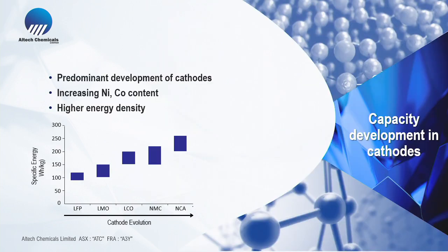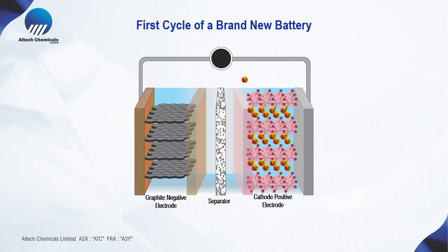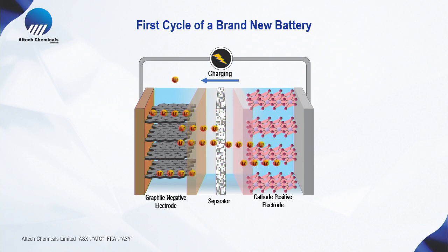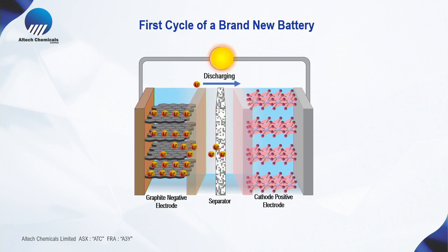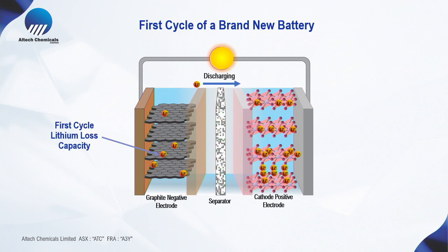So if you look at a battery, you've got a cathode, the positive side, and the anode side. Now, when you charge the battery, the first thing that happens is all the lithium ions go from the cathode side to the anode side. And that's when the battery is being charged. Now, when you're ready to discharge the battery, all the lithium ions move back to the other side. But what's interesting is about 8% of the lithium stays on the graphite, and it becomes inactive. So before you get the battery, 8% of the lithium is already inactive to the performance of the battery. And this is called the first cycle lithium loss capacity.